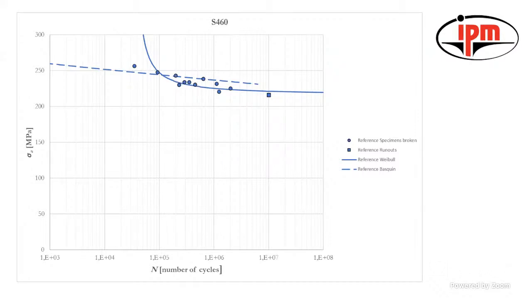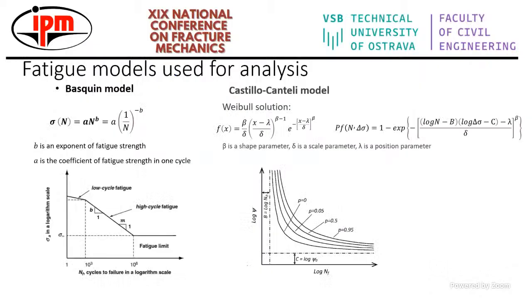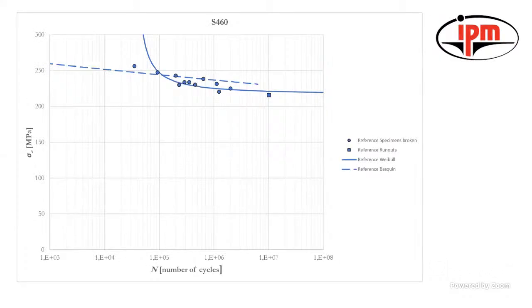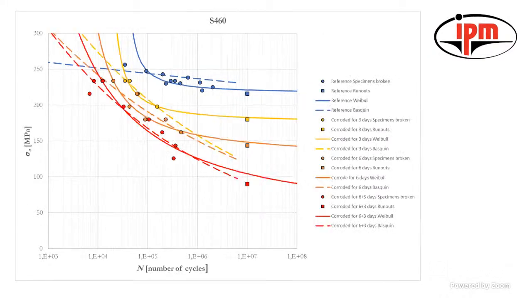Applied, and then the problematic part of the Castillo-Cantelli model is that it is described for a hyperbolic, almost hyperbolic, shape. This means that according to the rules, we start the Basquin evaluation from 10,000 cycles, and we need to start also for the Castillo and Cantelli model. Okay, this is the reference one, and then the comparison of all four situations after the exposure in the chamber.